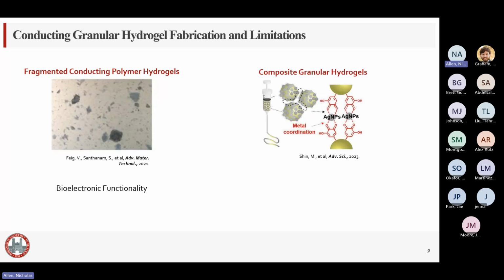Another method that researchers have used is composite granular hydrogels. Essentially, with this method they utilize non-conducting microparticle fabrication methods and non-conducting materials, but incorporate metallic or conducting polymer nanoparticles into the non-conducting hydrogel matrix. This method generates highly uniform microparticles. You can get very low standard deviation. They're very circular. So those limitations we saw in the other method, this second method does not have those issues.